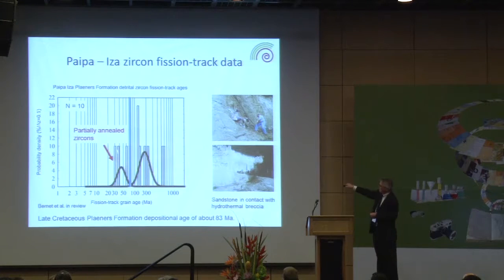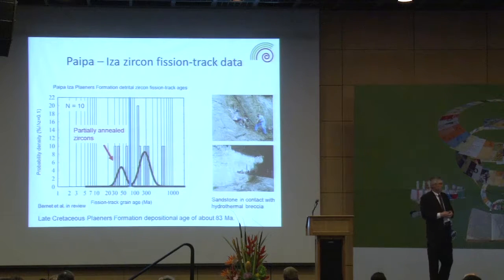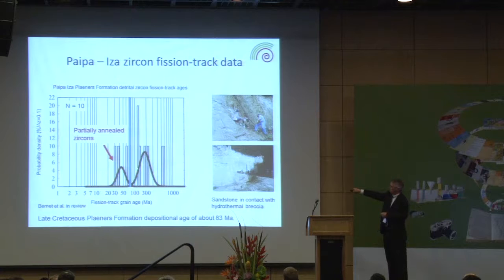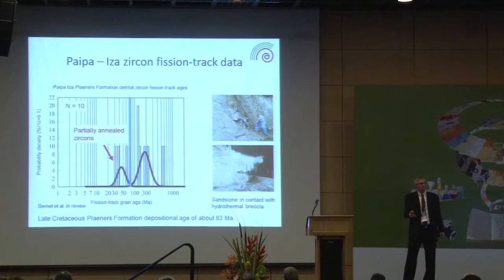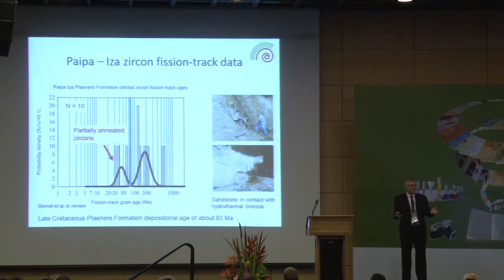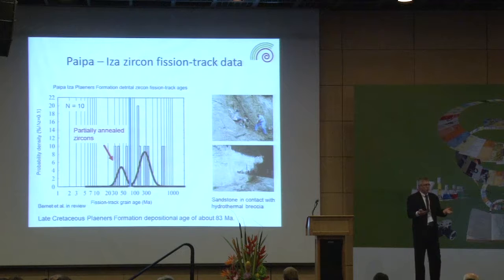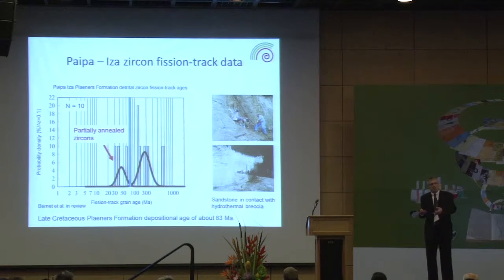And the blue line here basically indicates the age of deposition for this formation, which is about the late Cretaceous, about 83 million years. So we can see this one population here is definitely much younger than the age of deposition, which is an indication for the partial resetting. So the age itself, 54 or 50 million years, has no geological meaning, but it is a good indication that we had a partial resetting.